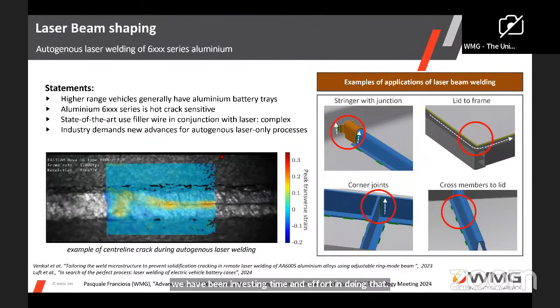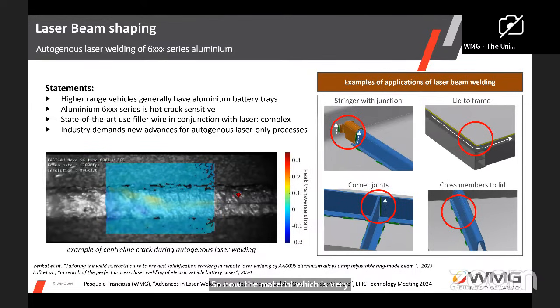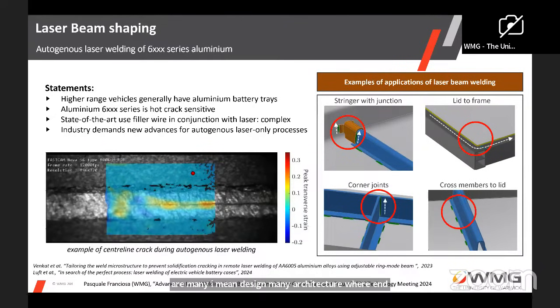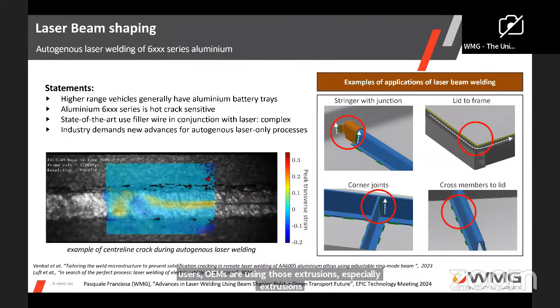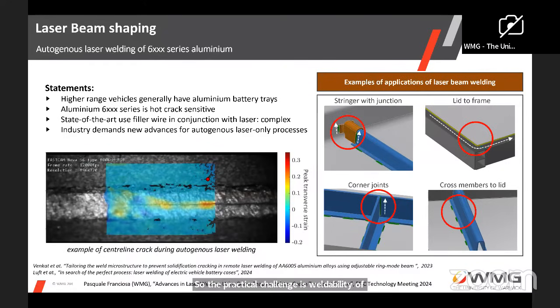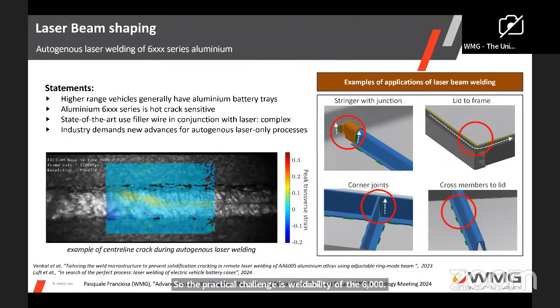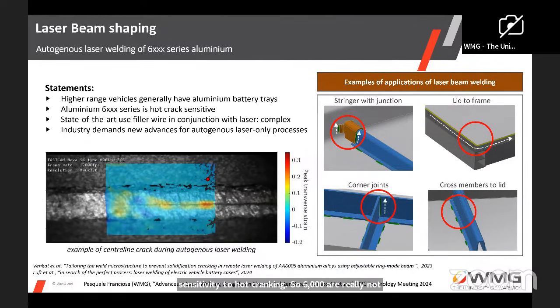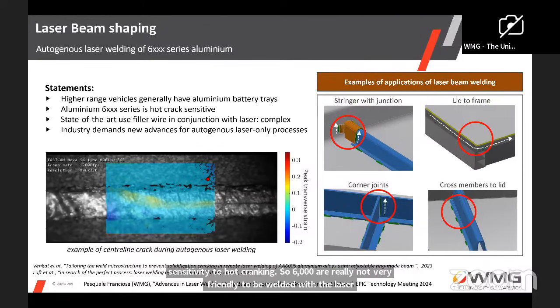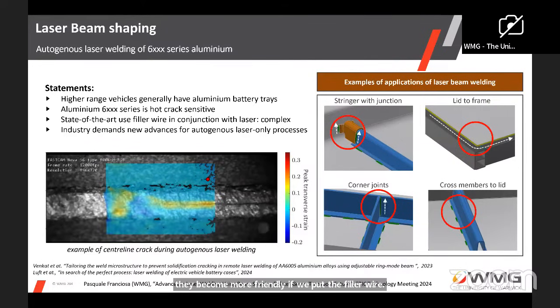So now the material, which is in very high demand these days, is aluminum. So 6,000 series aluminum, especially for producing battery cases, so battery trays. There are many designs and architectures where end users, OEMs are using those extrusions, especially for producing battery casing. So the practical challenge is the weldability of the 6,000. There is an evergreen challenge, which is the sensitivity to hot cracking. So 6,000 series are really not very friendly to be welded with the laser. They become more friendly if we put in filler wire. So then it becomes a hybrid process, laser plus filler wire.